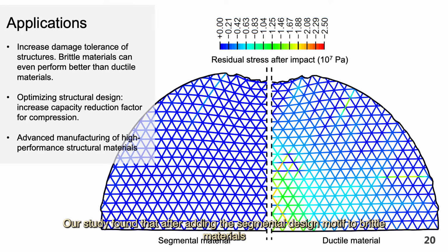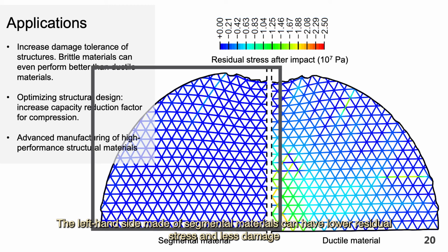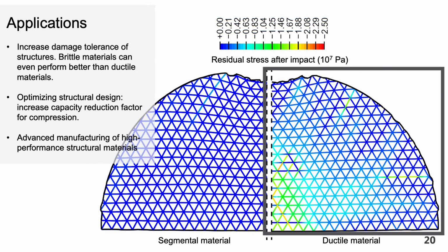Our study found that after adding the segmental design motif to brittle materials, the structure built with these brittle materials can perform better than those built with ductile materials. As shown in the figure here, this structure is subjected to impact. The left-hand side, made of segmental materials, can have significantly lower residual stress and less damage compared to the right-hand side, which is made of ductile materials.